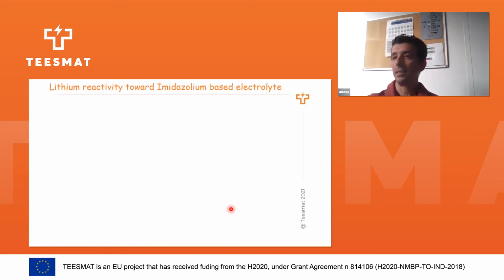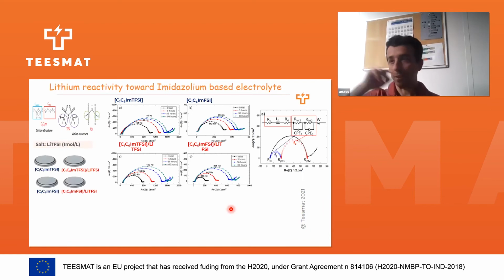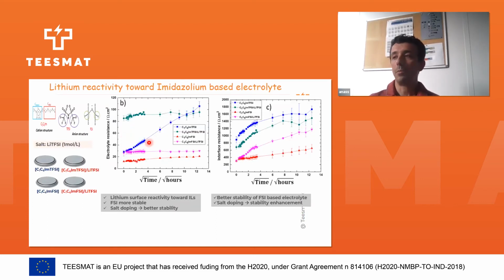The second part here, we studied in collaboration with other academic partners the reactivity of lithium toward these two kinds of ionic liquid. We measure the impedance in a symmetrical cell, and we can see how we age those cells at room temperature. We can see the evolution of the interface resistance and bulk resistance during aging, recording the electrolyte resistance and the interface resistance. Depending on the nature of the salt and the electrolyte, we can see some modification.